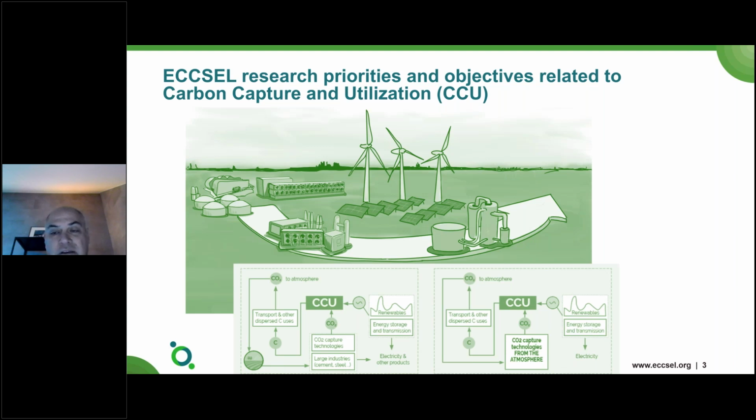Since formic acid, just like water, goes via the membrane to the other side, the anode, you don't get a very selective product. That's also one of the challenges in the electrochemistry of CO2 reduction, and also CO2 can cross over to the anode side, which is also not nice and has all kinds of side effects. You will see that when you scale up technology. You can do it at a very small scale, but as you scale up, my personal observation is that you get a lot of issues with these types of things, which you don't see in a very nice lab setup. But the crossovers are very painful things which can hamper current efficiency and current density, of course, as well, and product quality.